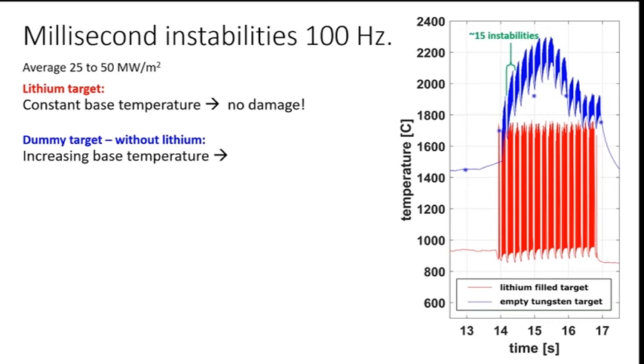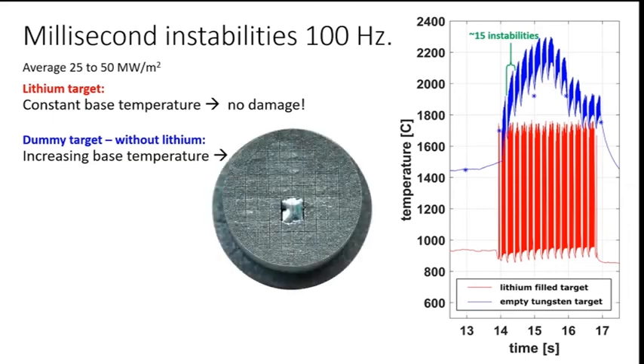Whereas the dummy target without lithium, you can see there the base temperature keeps increasing until about halfway, and then suddenly it seems to dip. And what you see there is actually melting. So there is a big melt pool of molten tungsten. The emissivity of that is lower, the infrared emissivity, and that is why the temperature seems to drop. And afterwards, you can see actually that we did make a beautiful drop of tungsten there on our target, which was, of course, unfortunate for the target, but it was a very interesting result.